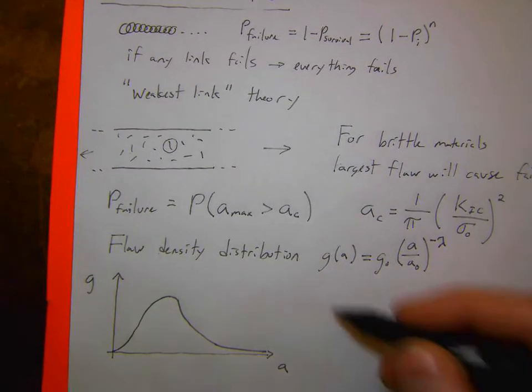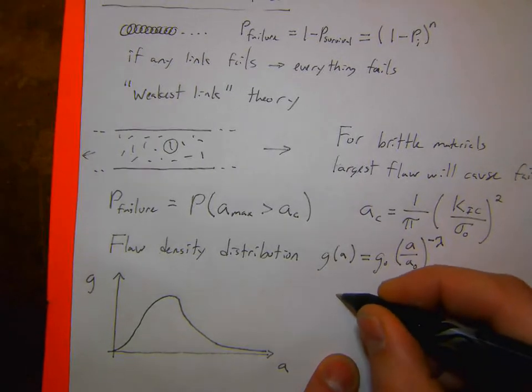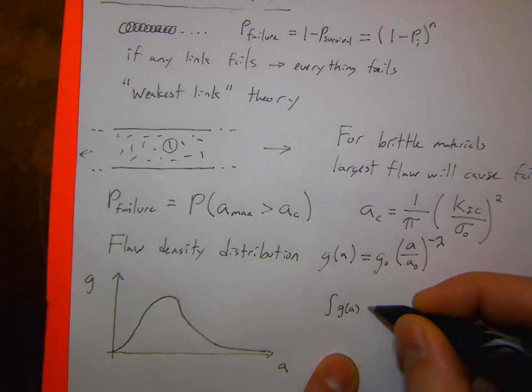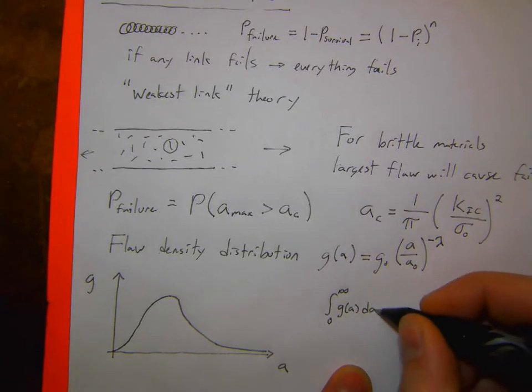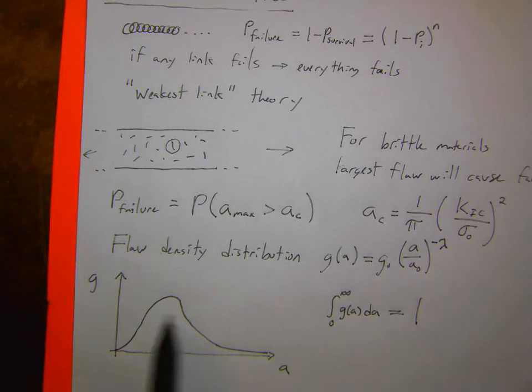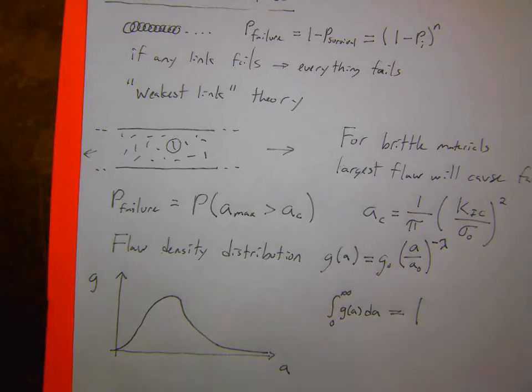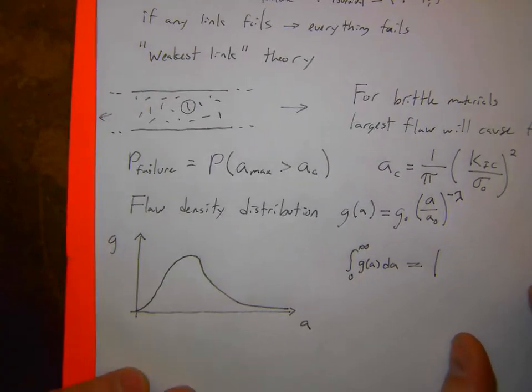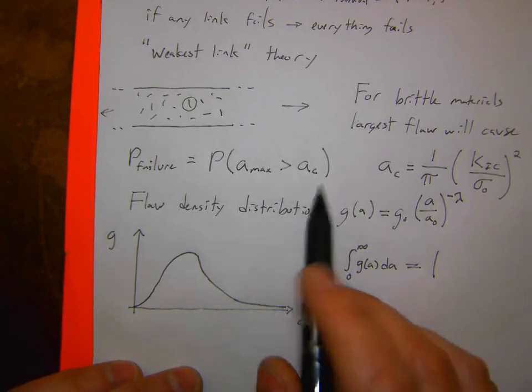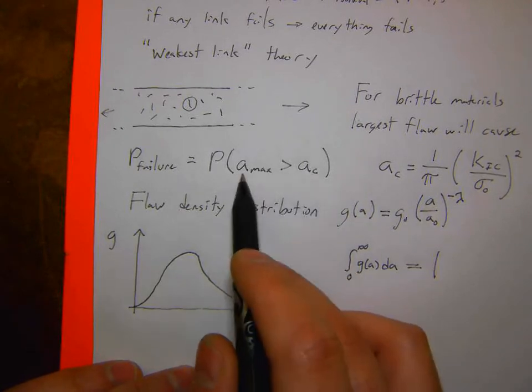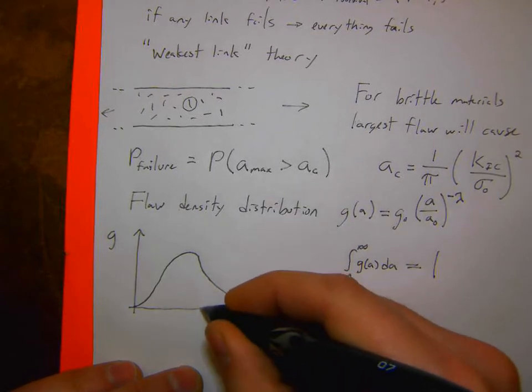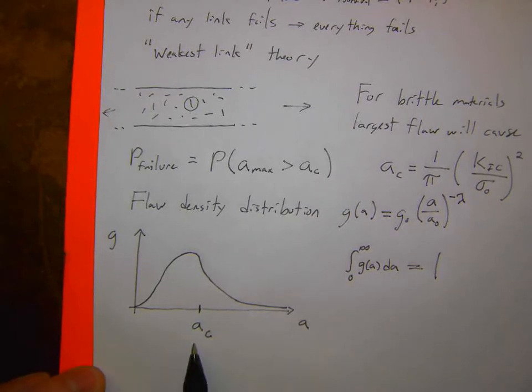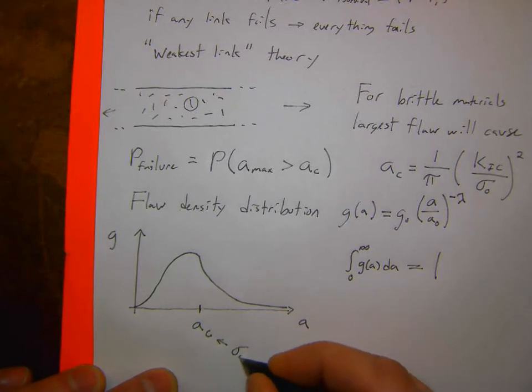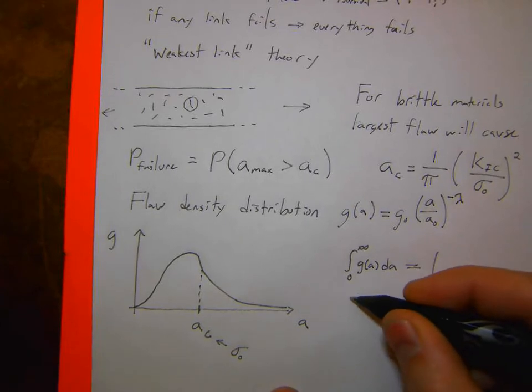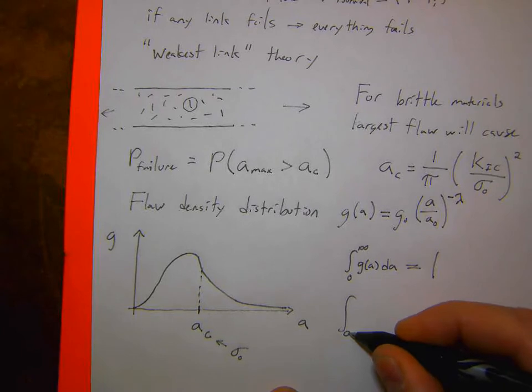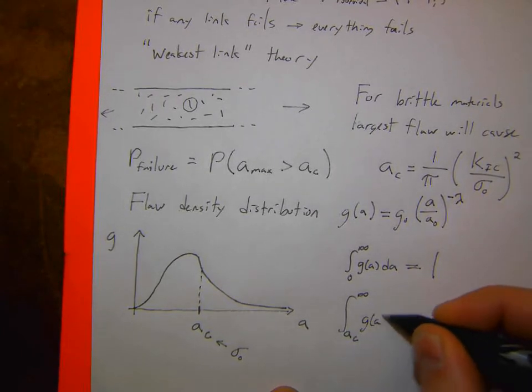So now I'm going to say that this is a density distribution. If I take the integral of g of a from 0 to infinity through all of the a's, then this is 1. So the whole area under this curve is 1. And if I take it now somewhere less than that, then I have something less than 1, some fraction of 1. And now what I'm basically looking for is, if I have some distribution of flaws and I want to find the probability that there's a flaw that's greater than a critical flaw size, I need to say, okay, what is my critical flaw size? So I have some critical flaw size that's now dependent on my far field applied stress. And I'm going to say the probability of there being some flaw greater than that is the integral from AC to infinity of that G of A dA.